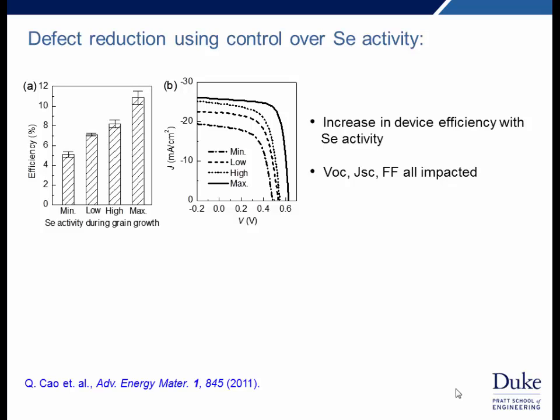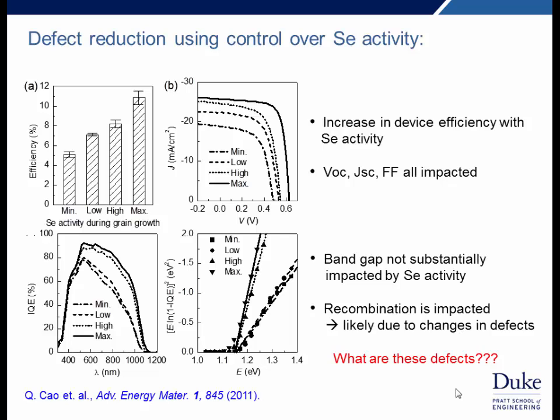And the change in performance is reflected in all the PV parameters, the short circuit current, the open circuit voltage, and the fill factor. Naturally, we'd like to understand where this is coming from, and a good place to start is the quantum efficiency curve. If we look at the long wavelength tail on this and plot it versus energy, we can extract the band gap and see that the Se activity does not affect the band gap of the material, but we do see substantially more suppression of the quantum efficiency at long wavelength, and this is associated with more recombination.